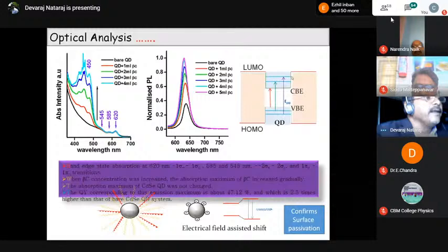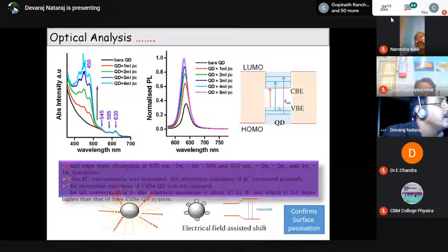To make sure of this, we have tested it by subjecting the samples to energy-dependent emission behavior. It means that I slowly increased the excitation energy of the emission process, and thereby monitored the emission trend. Suppose I use a photon which has an energy equal to the difference between the valence and the conduction band edge states, then the electrons are promoted exactly from the valence band edge state to the conduction band edge state. The electrons and holes are well confined.